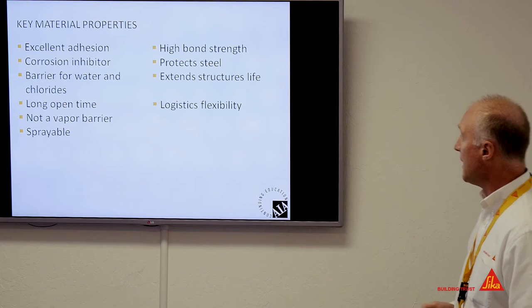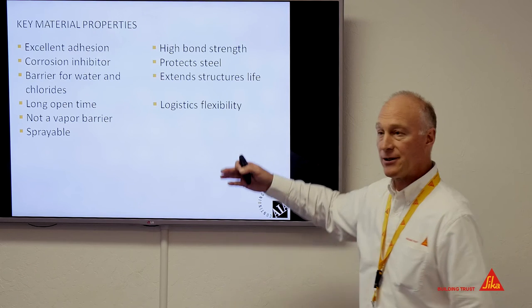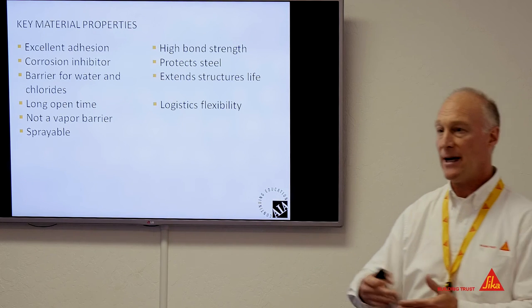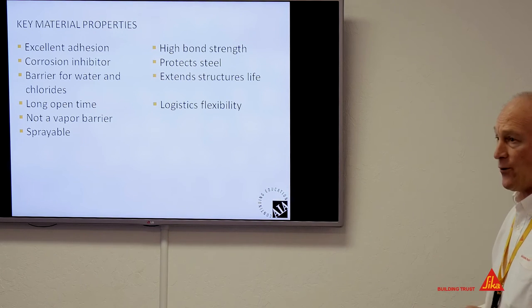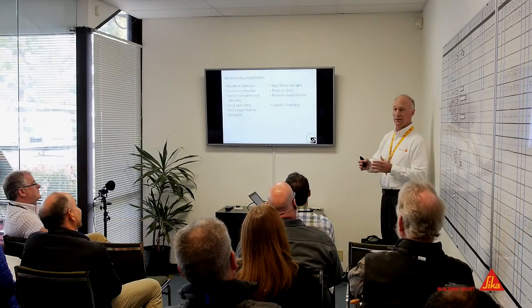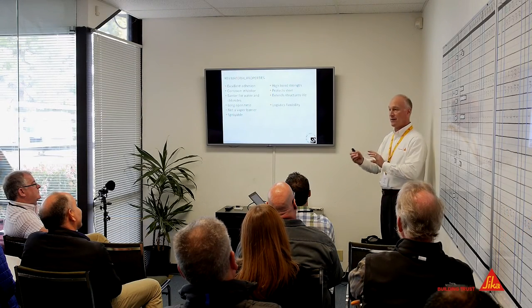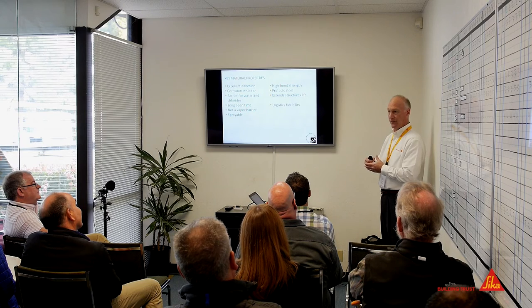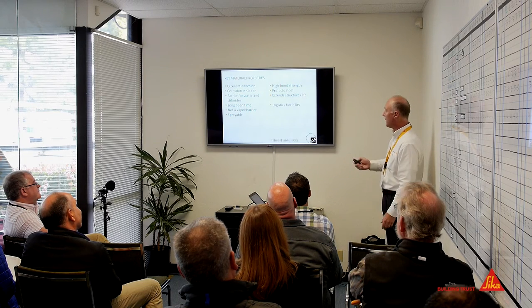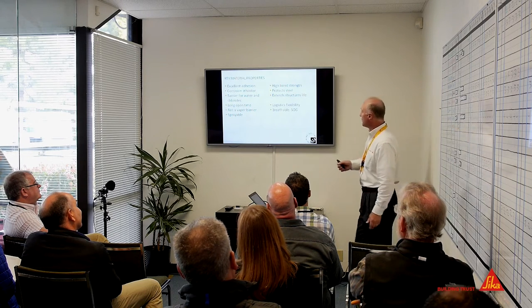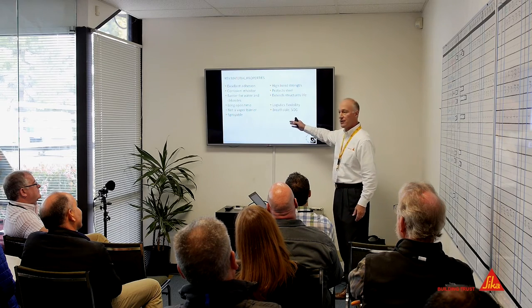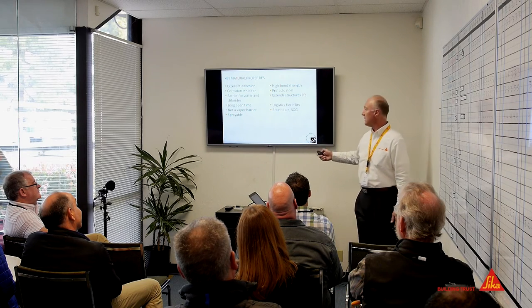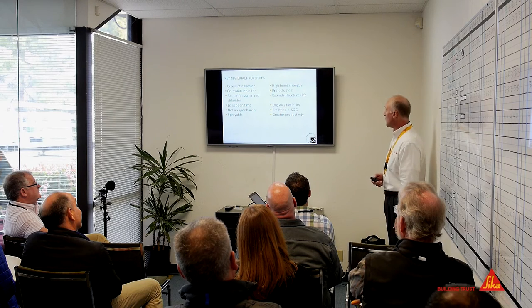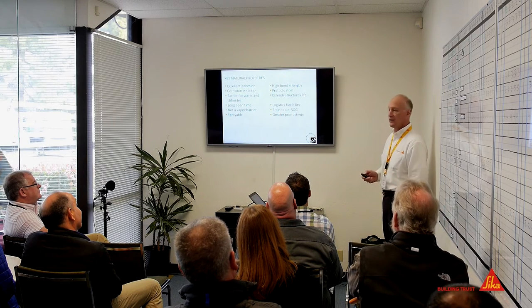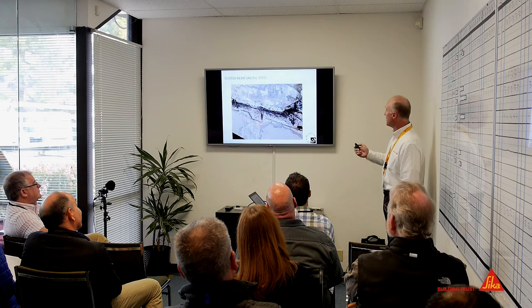A longer open time has more to do with the logistics and flexibility. You can place the material and come back the next day, and actually we'll form and pour this afternoon. A lot of times they'll coat the steel, put the form on, and then come back in the morning and place the concrete. So you don't have to do it within 20 minutes or a half hour. It's not a vapor barrier, so it's breathable, which means we can use these materials slab on grade. And sprayable is often useful, because you can get greater productivity. So here are some examples. This is where it's been coated on the steel.